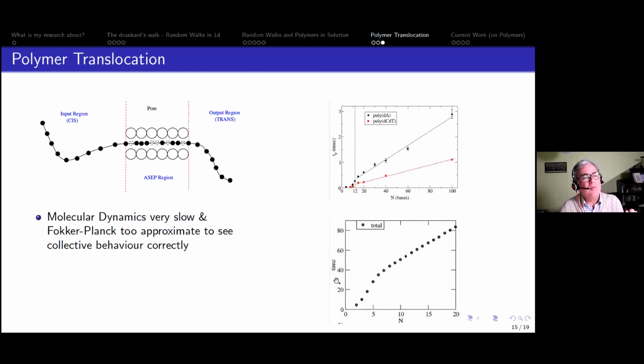And we found quite good qualitative agreement between our little numerical experiment and the true experiments. Whereas molecular dynamics might take weeks or months to do, our little simulation took of the order of 30, 40 seconds. So it would be not as good as an exact solution, but not bad.